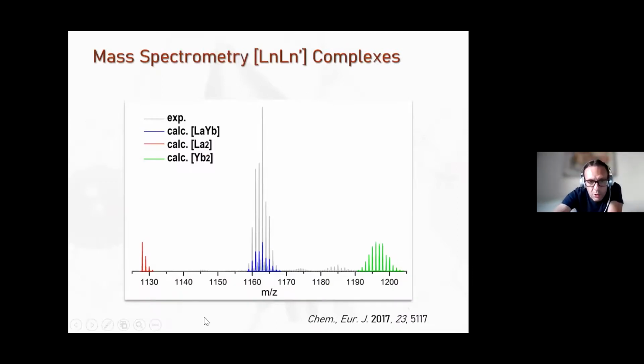Here is an example of how we use mass spectrometry to trace the selectivity in solution. In color are the expected signals for the various combinations of metals. In gray is an experimental trace. For this case, for example, we prove the absolute absence of any homometallic residue compared to the heterometallic one. We see that for many of our compounds, and then we start to see the appearance of homometallic marginal, let's say, or small traces when we approach the size of both lanthanide ions.